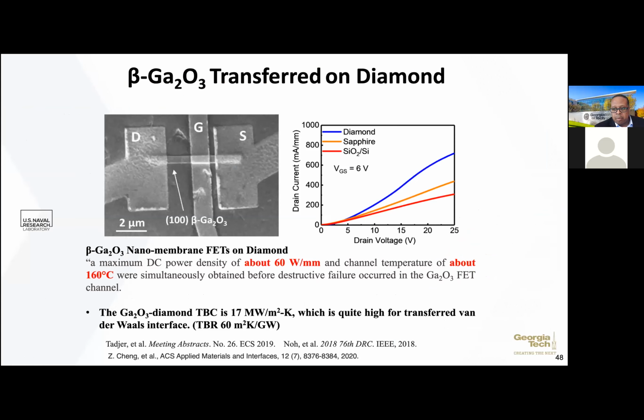Again, this is some work where we placed this on diamond. This is some work that we did with the Naval Research Laboratory. They were able to achieve power densities of 60 watts per millimeter with these transferred over to diamond. However, the thermal boundary conductance here is only 17 megawatts per meter square K. We believe that you can dramatically increase this in order to improve the overall heat dissipation from these structures.